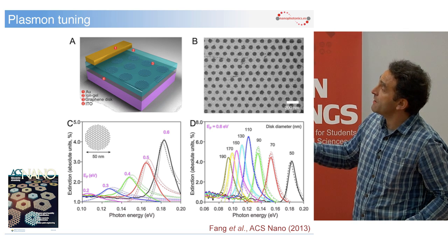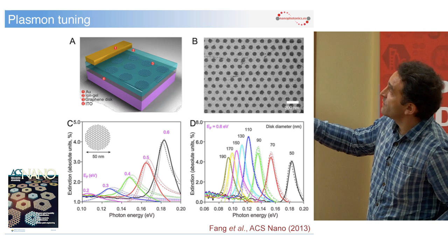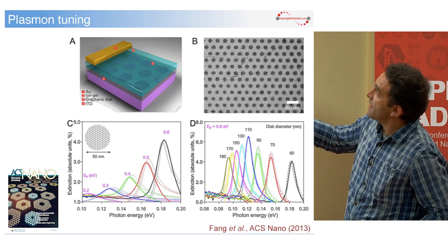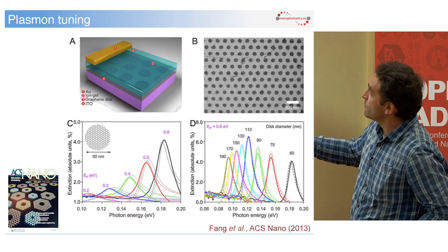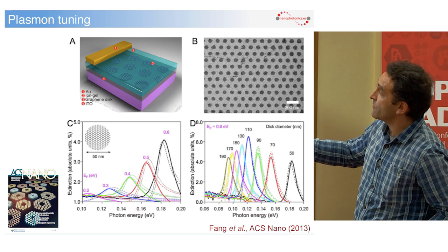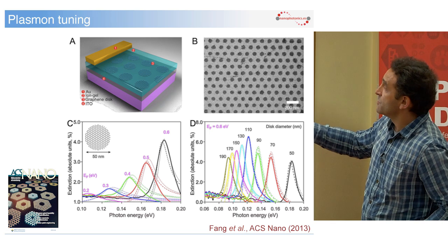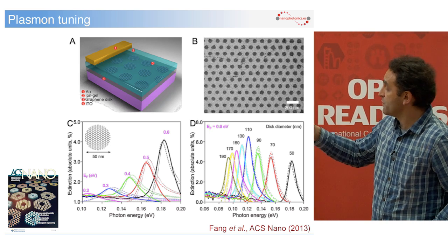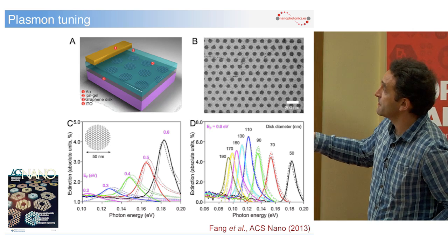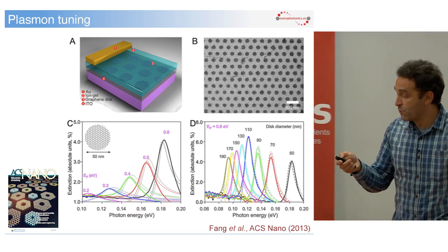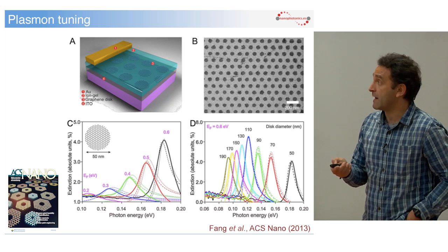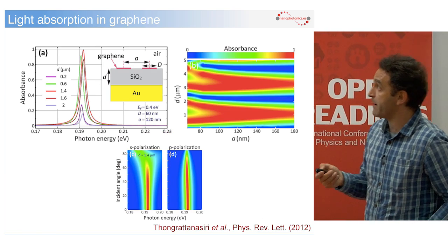And then what you do here is you tune through this gating device. You inject charge carriers into this graphene structure, and by doing that, you modulate the position of your plasmon resonances. So all of this analytical theory I show you here is basically the dashed lines, two different flavors of the theory, which compare very well with the solid curves, which are direct from experiment.